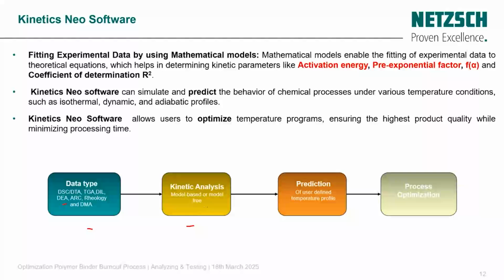And also we can use the model-free for the single step, and sometimes, with some exceptions, for the multi-step. And after doing the kinetics analysis, we can get the kinetics parameter data, for example, the activation energy, the pre-exponential factor, the reaction model, and the coefficient of determination, which is the R square, which gives us an idea about the goodness of the fit. Then we can go to the third stage, the prediction, where we can do the prediction at different temperature conditions: isothermal, dynamic, and adiabatic.